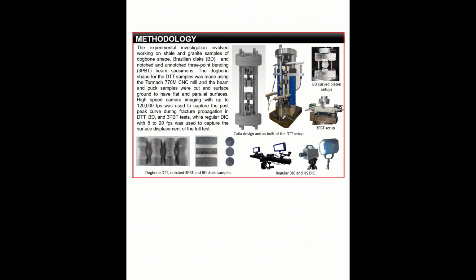Next, if we look in depth into the research methodology used for this study, the experimental investigation involved working on shale and granite samples with dog bone samples and notched and unnotched 3-point bending samples and BD samples. The dog bone shape for the direct tensile samples was made using the Tormach CNC mill, and the beam samples and the BD samples were cut and surface ground to have flat and parallel surfaces.